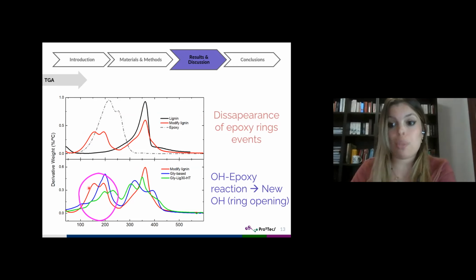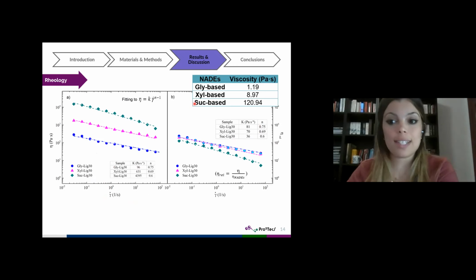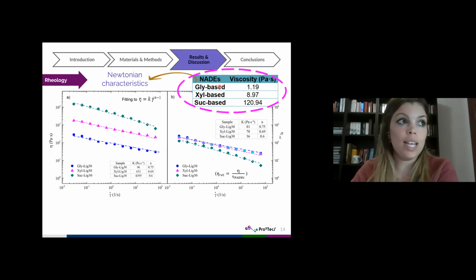Well, now we are going to see the rheological behavior of these compounds. As we can see in this table, NADES can reach such high viscosity values that limit their use in many applications, being able to modify these properties, as I detailed earlier, by varying the amount of water. In general, as can be seen in the table, Newtonian characteristics with important differences in viscosity were obtained when modifying the hydrogen bond donor compound. I mean, obtaining very high viscosity values for the sucrose-based sample compared to the other ones.